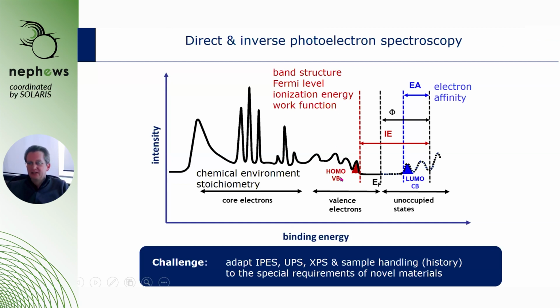So either it could be the valence band, as said before. If you have a molecular material, it could also be emission from the highest occupied molecular orbital, or HOMO, HOMO-1, 2, 3, and so on. If we also measure the secondary electron cutoff from our sample, essentially the energy of electrons just leaving the sample with almost zero kinetic energy with respect to our spectrometer, we can determine the work function of our sample experimentally and directly.